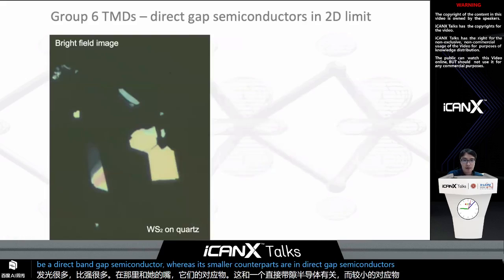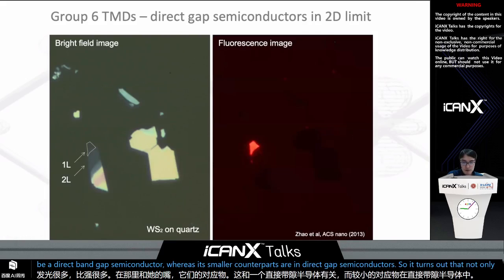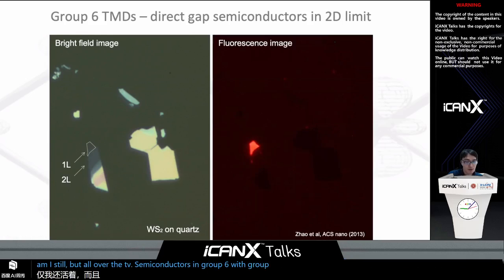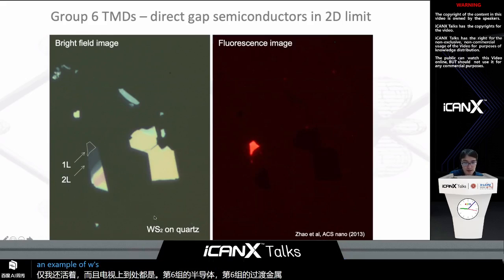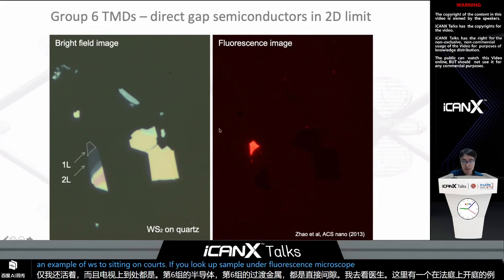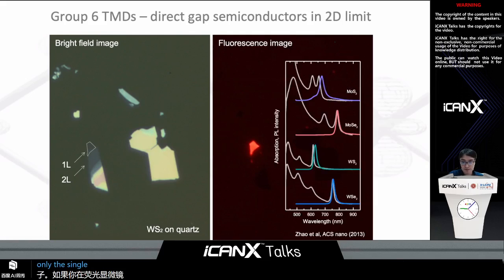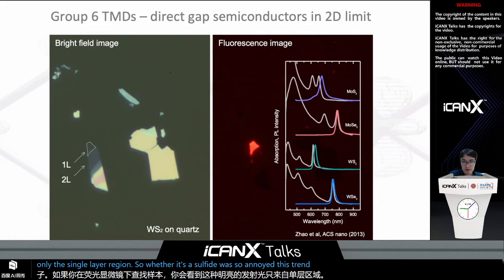So it turns out that not only MoS2, but all the 2D semiconductors with group 6 transition metals are direct gap semiconductors. So here's an example of WS2 sitting on quartz. If you look at the sample under a fluorescence microscope, you see this bright emission coming from only the single layer region. So whether it's a sulfide or selenide, this trend turns out to be true for these group 6 TMDs.